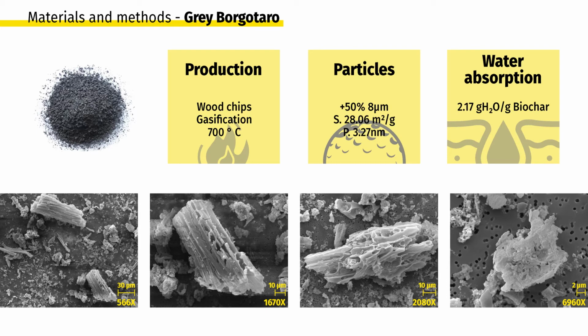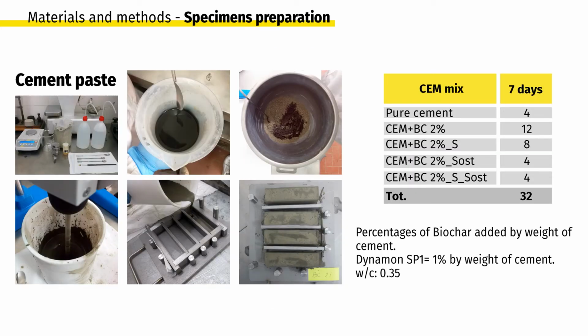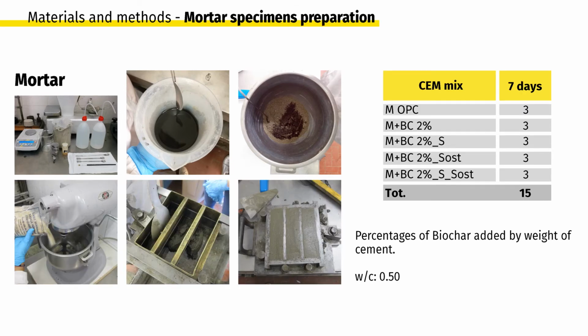As said before, porosity gives the material the capacity to retain water. Specifically, Gray Borgotaro can absorb 2.17 grams of water per gram of biochar. In this work, the biochar was used as a filler and a substituent of cement powder and mixed in water or in the dry manner with the cement powder. An optimized percentage of 2% of biochar was used, both for cement-based specimens and mortar specimens.